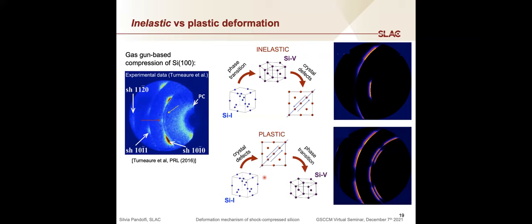hypothesizing a plastic deformation preceding the phase transition, this implies that the system would relax towards a hydrostatic state before the phase transition. So this would actually relax the condition of preferred uniaxial growth of the high pressure phase. And this actually just means that in our simulation, we've allowed and included the reflection from all the different possible equivalent orientations between the silicon one and silicon five.